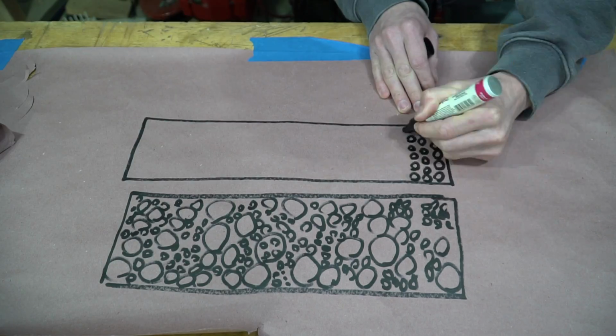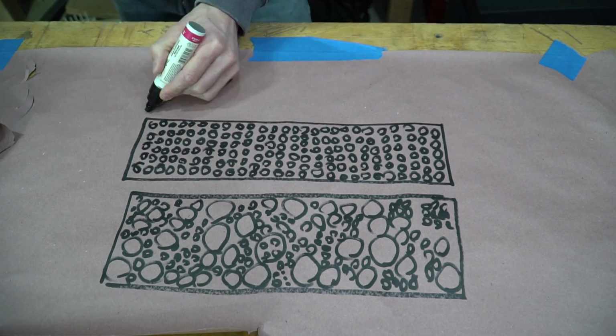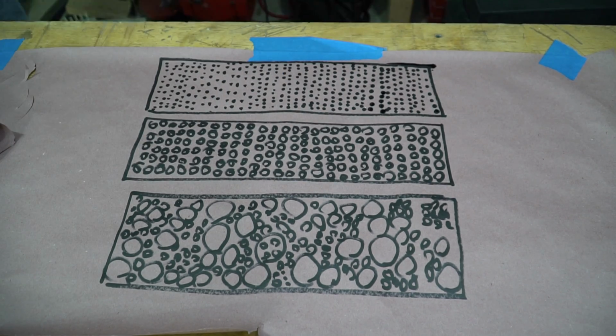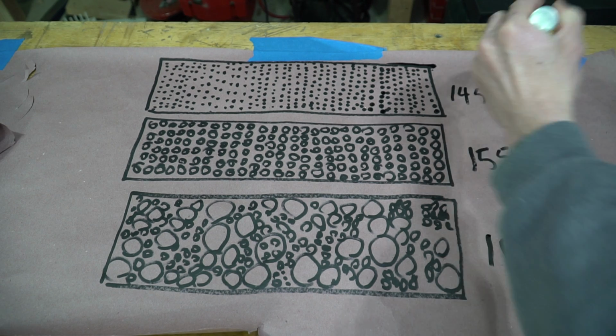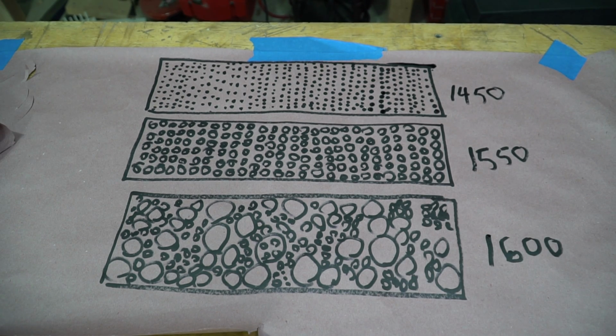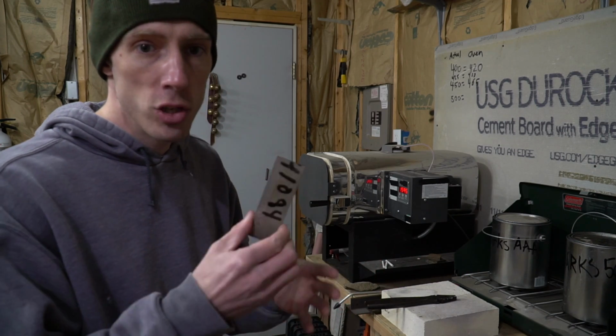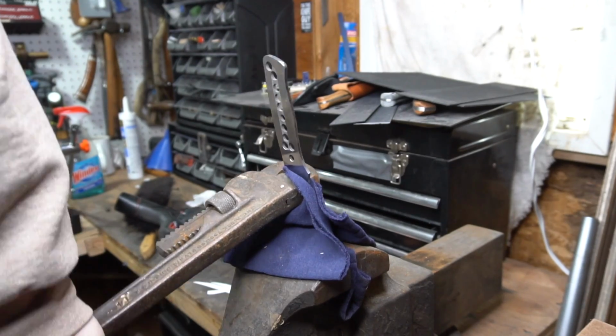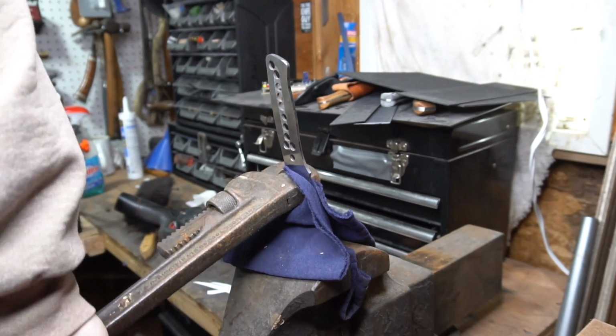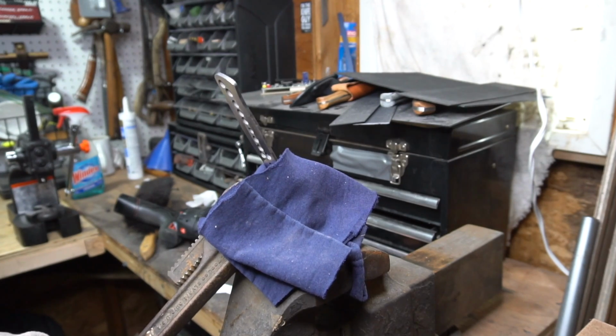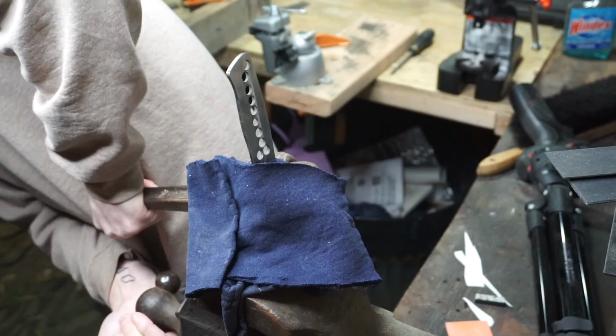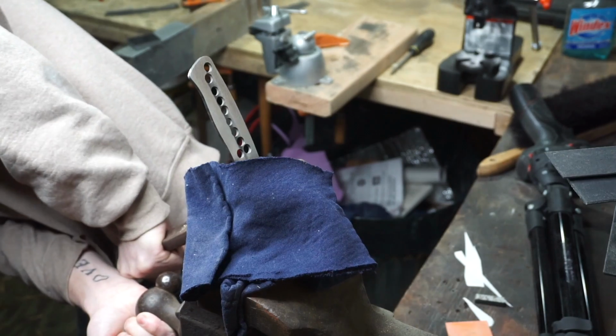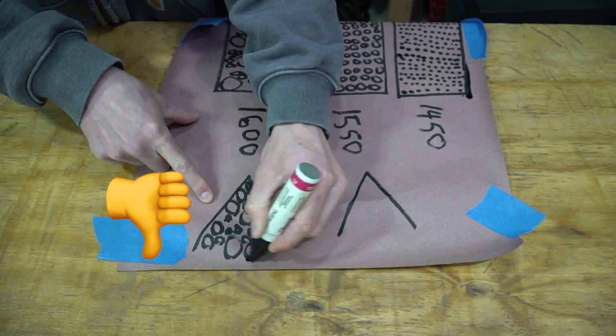Now the idea behind thermocycling is that by doing these thermal cycles, we actually redistribute those grains and we make them physically smaller. This will do a couple of things for us. Not only will it give us a much stronger knife that we're able to leave a lot harder, which is good for knives, with the same strength, because the smaller and tighter the grain structure, the stronger the steel itself. It'll also give us things like better edge retention. It'll make the knife easier to sharpen, and it'll allow the knife to get physically sharper.